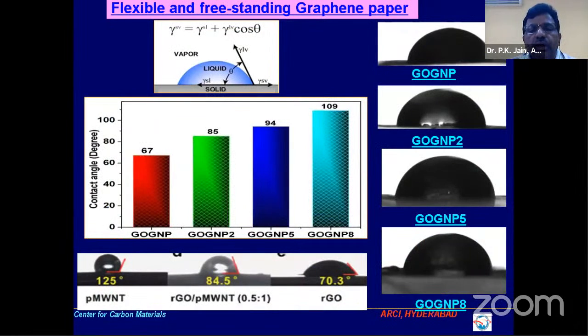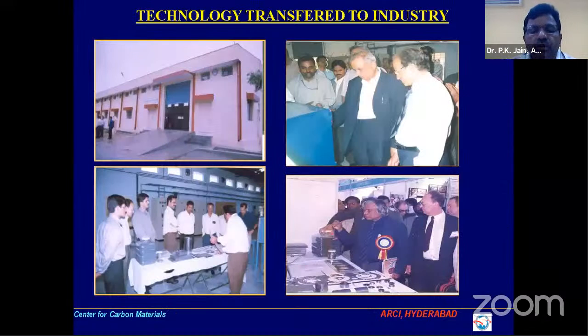Another technique, the processing can lead to a graphene surface with contact angle from 67 to 109. This shows that it can be converted from hydrophilic to hydrophobic, and that is also a very interesting study. Now this technology was transferred to industries, and some important prominent visitors also visited our lab.